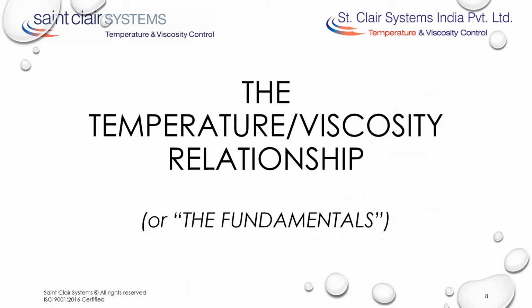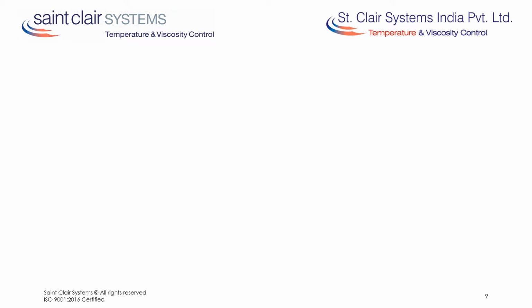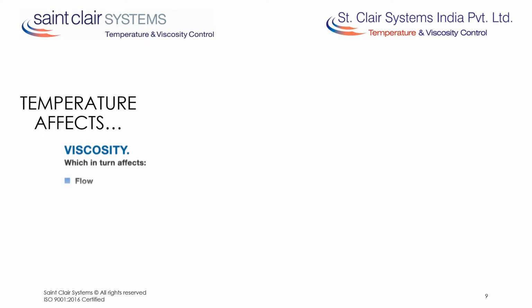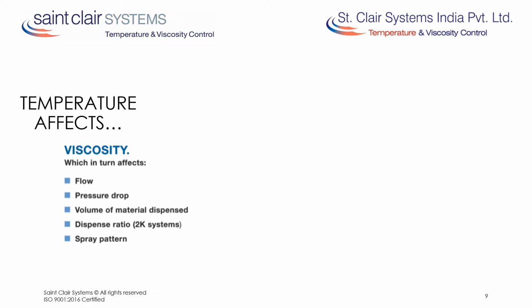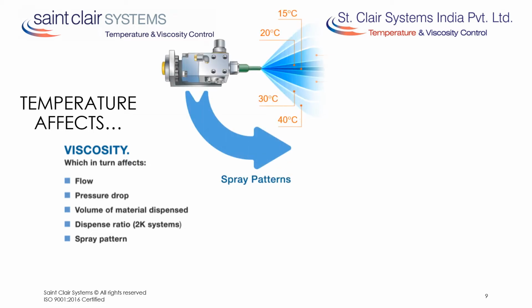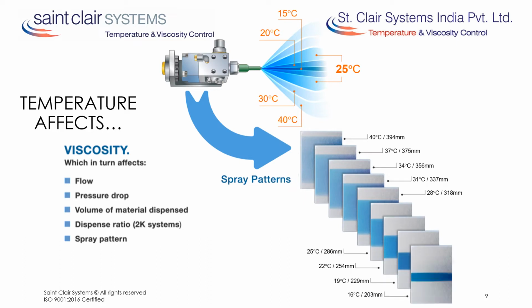So let's look at the fundamentals that create fluid dispensing issues in the first place. We're often asked why we focus on temperature, and the answer is that temperature affects viscosity, which in turn affects flow, pressure drop, volume of the dispense, and the ratio in the case of 2K materials. But most of all, the spray pattern. Here we can see how the spray pattern changes with the width increasing proportional to the temperature, but this phenomenon is actually caused by the change in viscosity.